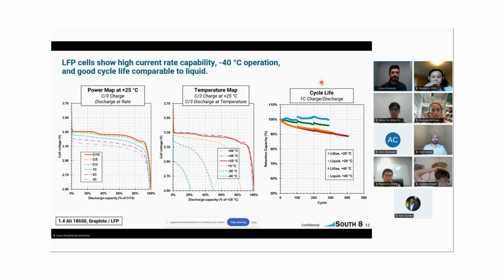This is an LFP cell with a graphite anode, fairly low capacity, only 1.4 amp hours. Again, these are just R&D cells that we're procuring. Good power capability, everything from C/10 to 3C, delivering pretty much 100% of your nameplate capacity. For temperature mapping, you can see a recurring theme with the power, temperature, cycle life. I try to keep it all standardized to keep it easy. For the temperature mapping, going from plus 60 to minus 40 is no problem for us.